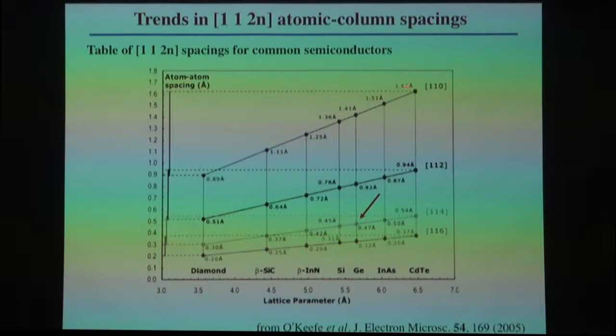So, okay, 110, the spacings are well known. You could come from 1.6 down to 1.4, 1.25, down to 0.89. We saw examples from the work of O'Keefe where he was doing the focal series reconstruction, and 0.89 actually overlaps with cadmium telluride. So then you could do the 112s, and so the 112s in germanium, 0.82 angstroms, 112s in silicon, 0.78 angstroms. Put an arrow here because these days, depending on the particular microscope and whether you believe the line scans, people are now starting to resolve with the latest FEI microscopes, and now with the Grand ARM 300 kV microscope, JEOL is actually just able to resolve 0.45 angstroms silicon dumbbells in the 114 projection.